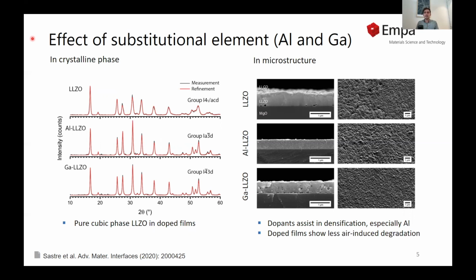We investigated the addition of these two substitutional elements and their impact on the crystalline phase and the microstructure. Here on the left, we have the XRD plots of the pure LLZO, the aluminum substituted LLZO, and the gallium substituted LLZO. We observe that in both the aluminum and the gallium doped LLZO thin films, we obtained a pure LLZO cubic phase. We also observed in the microstructure that the addition of such a substitution element has an impact on the densification of the films, especially those with aluminum. Also, the degradation on the surface seems to be mitigated by the addition of substitutional element.